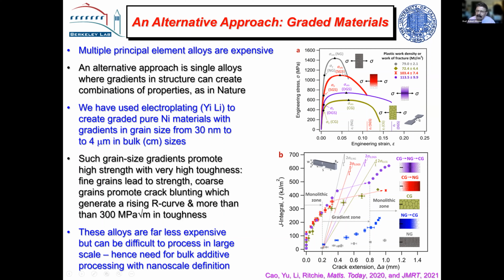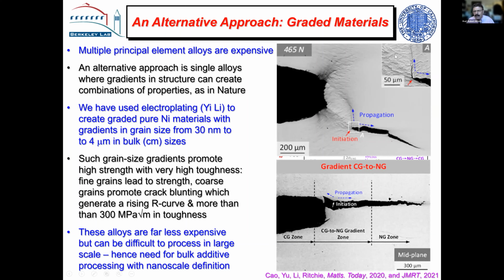So this is an intriguing way to go. It's much cheaper in terms of elements, but you've got to make them. And that means you're going to need to use additive techniques and so forth. So it's beginning to become feasible, but it's a much simpler way to go. And if you look at how the cracks grow, the fine grain material, of course, gives you high strength. But in addition to this, or rather, instead of the strain hardening we've talked about before, in the coarse grain structures, you get this massive crack blunting, which is very effective for toughness. So again, a slightly different mechanism, but you can generate this combination of strength and ductility